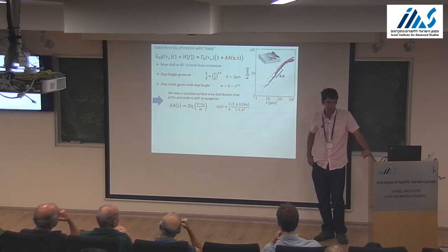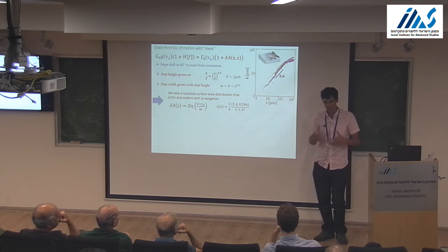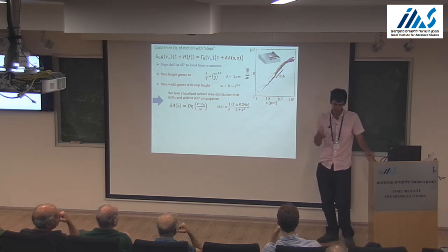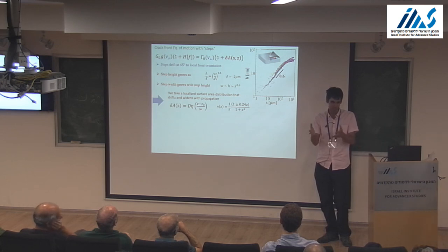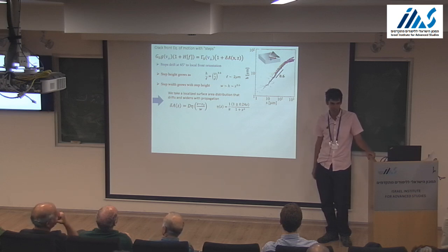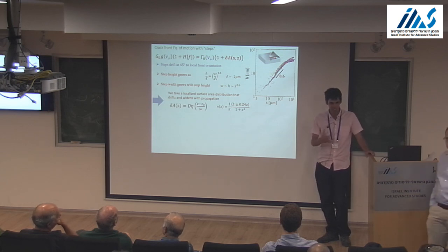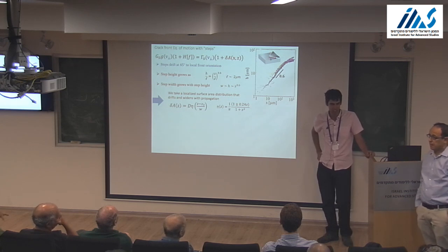So I think usually what happens, but again, I'm saying only from what I've seen, is that you can have many microbranches or branch lines which decelerate your crack, and then you go over to a faceting regime, and the two regimes can be intermittent in the same sample. So it's not a very well defined transition.